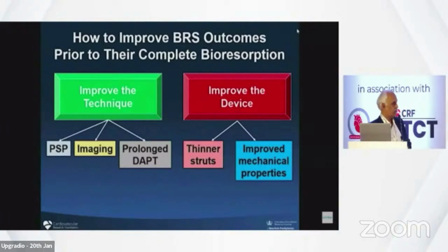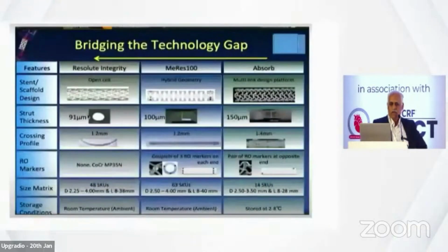So it's bed preparation. You prepare the bed well, you take the appropriate size and do a proper post-dilatation. With imaging, you see that there is no under-expansion or malapposition. Use prolonged DAPT, use thinner struts, and improve the mechanical properties. Probably that will do better. So in this direction, surprisingly, our own Indian company was working on this, Meril's MeRes100. This is a Meril company.